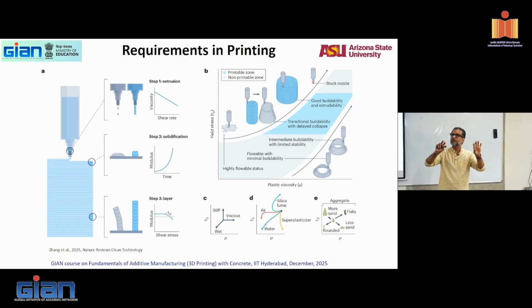By spreading these particles farther apart, what are they doing? These two cement paste particles are sitting like this. Superplasticizers, because of this phenomenon called steric hindrance, some of you would have heard in your classes, simply break this apart. They just go away, which means the contacts are broken. When the contacts are broken, yield stress comes down because you've broken the network. That's all you have done.